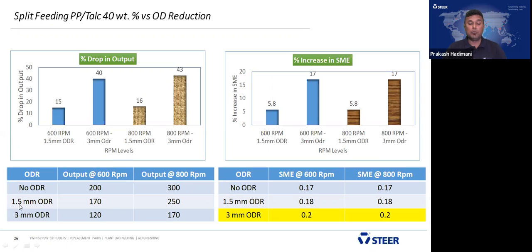And after doing 1.5 millimeter OD reduction, there's a slight drop in the throughput: 170 kg per hour at 600 RPM, and 250 kg per hour at 800 RPM. After doing the third case, 3 millimeter OD reduction, meaning 1.5 millimeter per side, we are getting 120 kg per hour at 600 RPM, 170 kg per hour at 800 RPM.